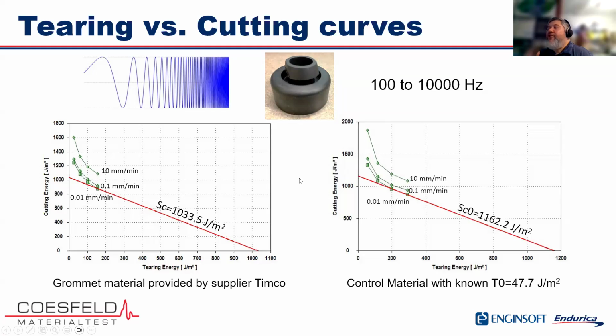The story for this one was that when you use a grommet in a vibration application, the amplitude of the vibrations can be quite small, which means you have a very large number of cycles, but you still want to know that you're not going to have fatigue problems. So if we just measure the fatigue limit, we can make sure that for the grommet we stay below the fatigue limit. Now, in this case, for the control material, we know that the fatigue limit was 47 joule or 48 joule per meter squared.